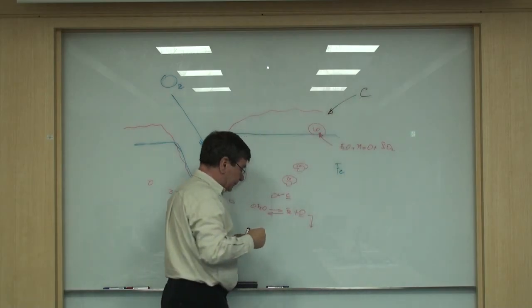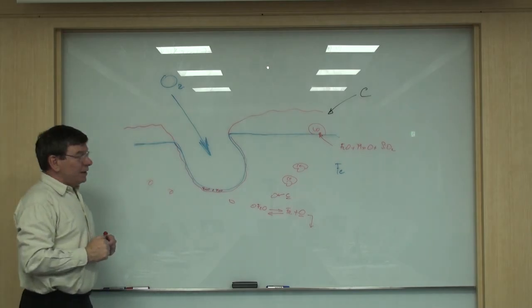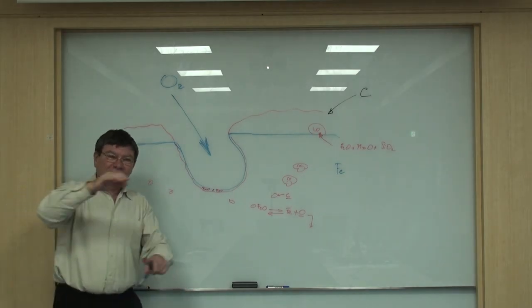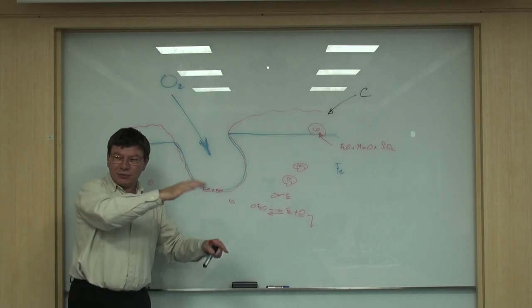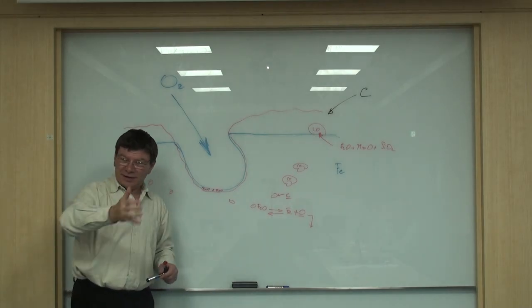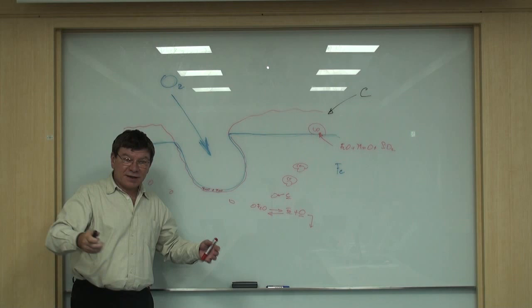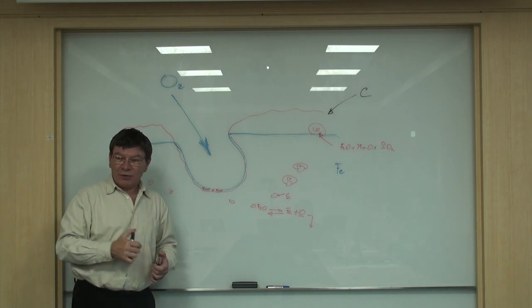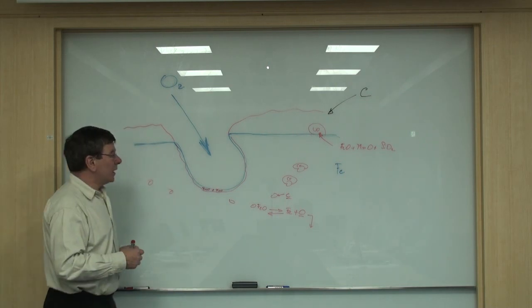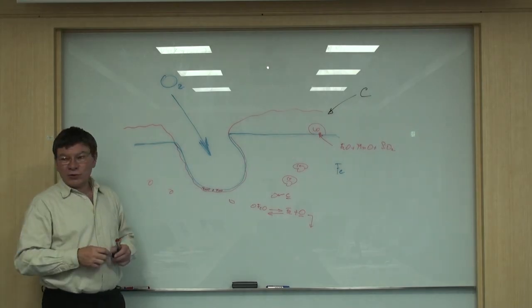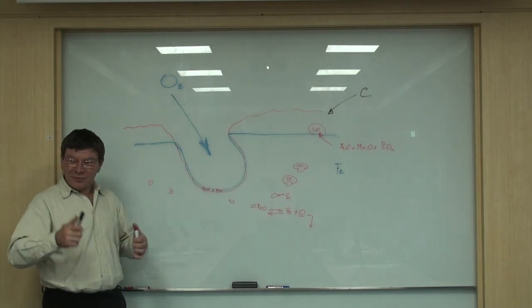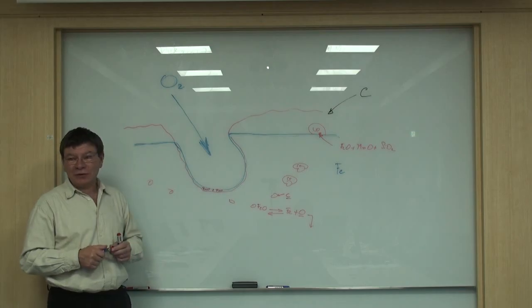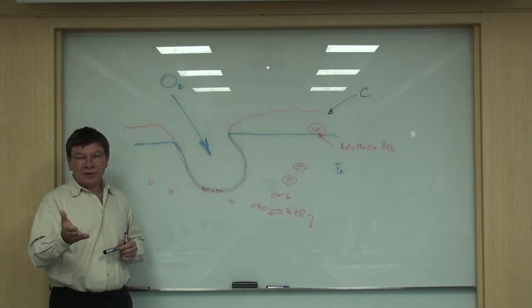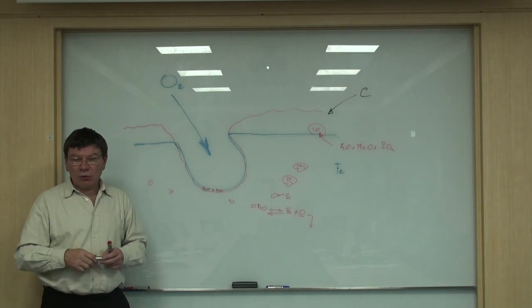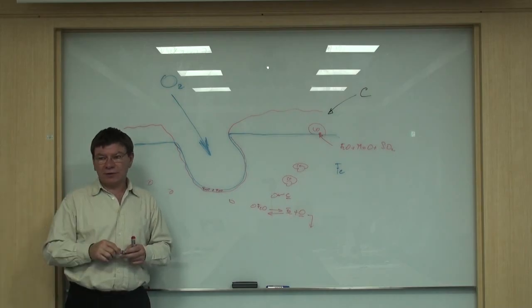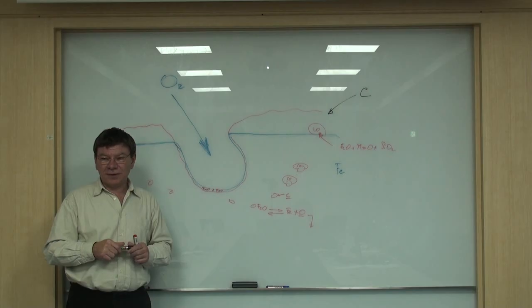Carbon injection. Yeah. And if the slag is foaming, then we can increase the voltage. So we can increase the power. And then, you see? This is, let's say, the origin of modern electric steel making. Then Fuchs arrived with the water-cooled panels, and then now you know that one furnace is able to produce 1 million ton, even more. At the origin, a conventional mini mill was able to produce at least 200,000 tons a year, yeah, in the 70s.